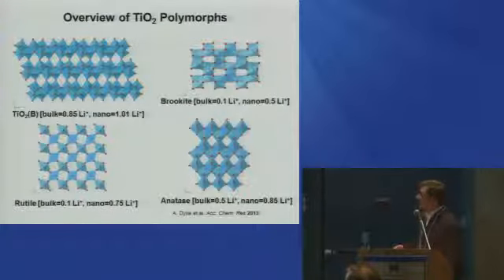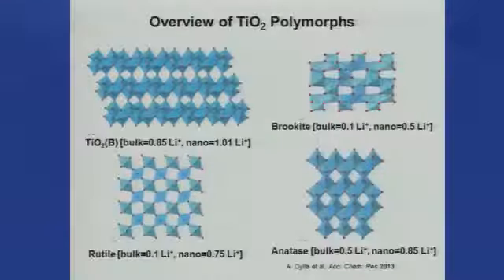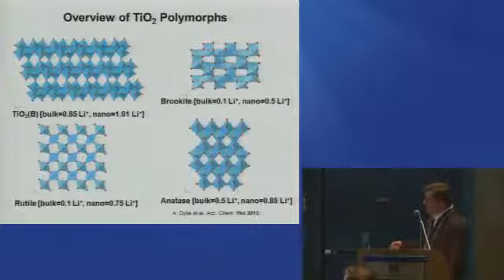Okay, so we summarized all of this in this nice accounts article by my postdoc, Tony Dylla. But what you find is if you actually look at the amount of lithium that you can store in TiO2b of these different polymorphs, the TiO2b is very interesting because in the bulk, you still start to access very high lithiums, where you get roughly 0.85 lithiums per titanium site. If you go to smaller nanoparticles, you actually can lithiate 1 lithium per titanium site. Other structures, it's well known in the bulk, they don't lithiate very well, but if you go to smaller sizes, it's now been shown by Wagemaker and Bruce Dunn and others that you can actually start to access more stable, kinetically stable, higher degrees of lithiation in these materials.